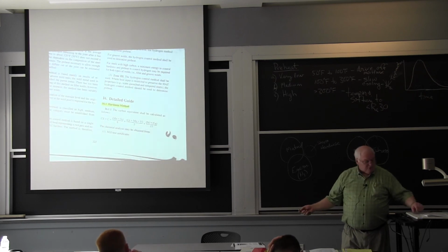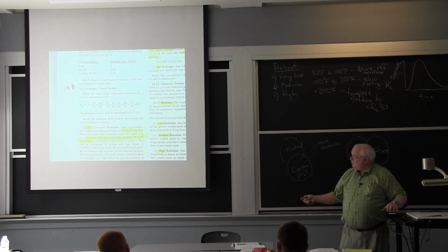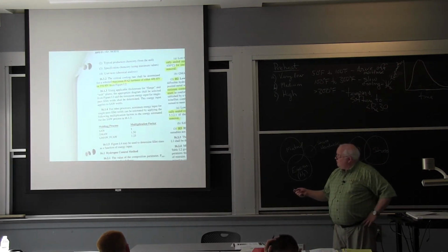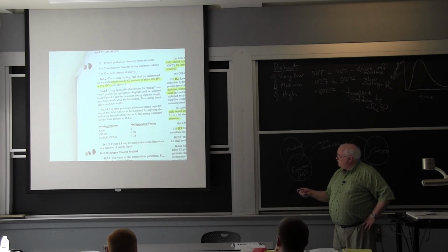Now, that's the hardness method. Going through here, you use the carbon equivalent and you look at another plot and determine whether you have a maximum heat affected zone hardness of 400 or 350 Vickers from figure 1.2. Well, it turns out 400